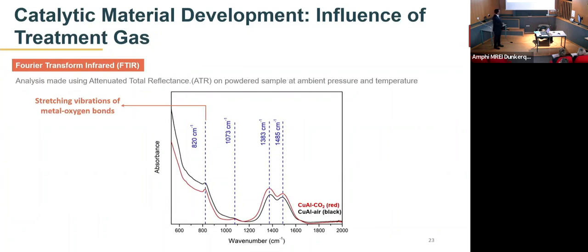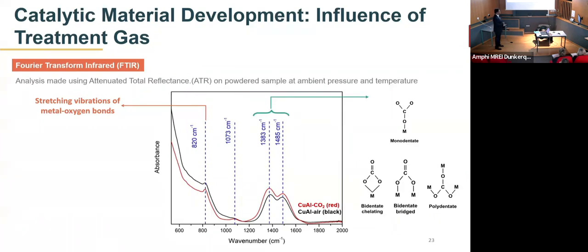So in the FTIR analysis for the CO2 treated sample and the air treated sample, we first see a band at 820, which is generally associated with the stretching vibrations of the metal oxygen bonds. The bands that we see at 1383 and 1485 are generally associated with different species of carbonates, could be monodentate, bidentate, or polydentate. While at 1073, we see a peak only for the CO2 treated sample, which is in red, which is associated with the bidentate carbonates. So with this analysis, we assured that there is the formation of bidentate carbonates in our mixed oxide sample when it is treated under the flow of carbon dioxide, and therefore could have helped us in NO reduction activity, specifically under the dry reaction condition.